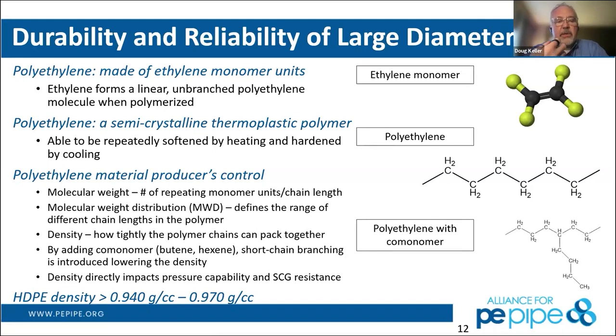This is very similar to a metal chain, if you want to think of it that way, with each individual link of that metal chain being an ethylene monomer in the case of polyethylene. So that's how we make polyethylene, by stitching those ethylenes together. Polyethylene is a semi-crystalline thermoplastic material. By semi-crystalline, we mean that it has both a crystal or an ordered structure and an amorphous portion, which would be a disordered structure. In addition, it is a thermoplastic, which means that it can be heated repeatedly without damaging the material, so that we're able to both form it into a pipe or into a fitting, and then fuse a pipe to a pipe or a pipe to a fitting using heat.